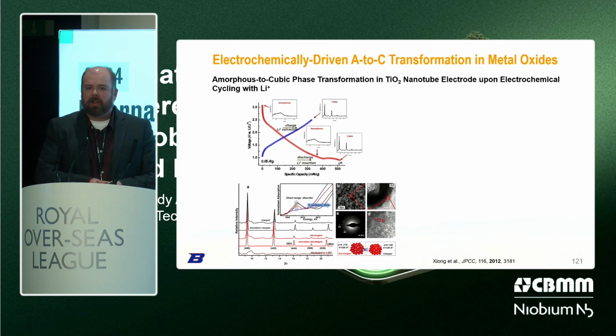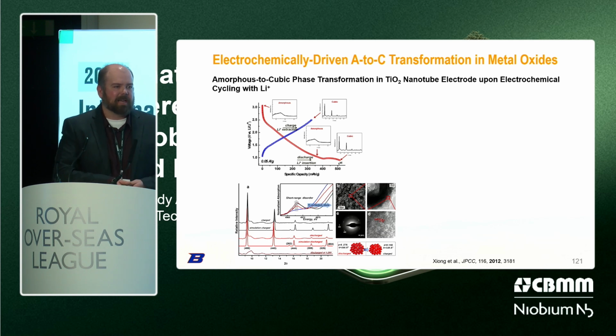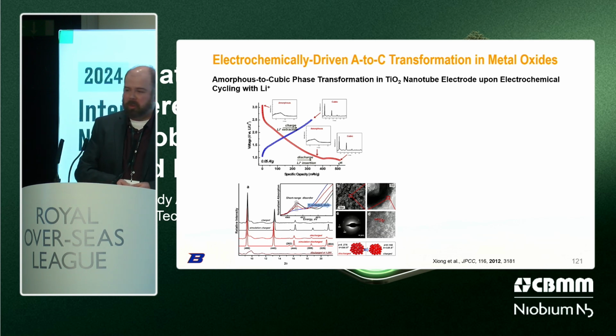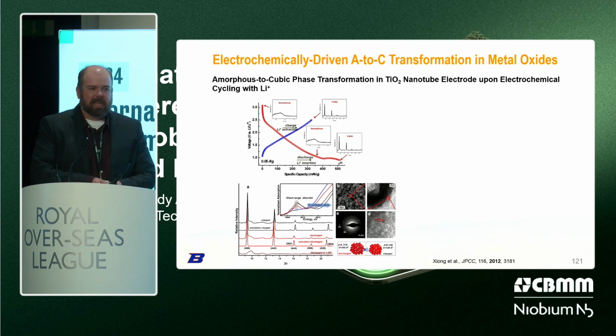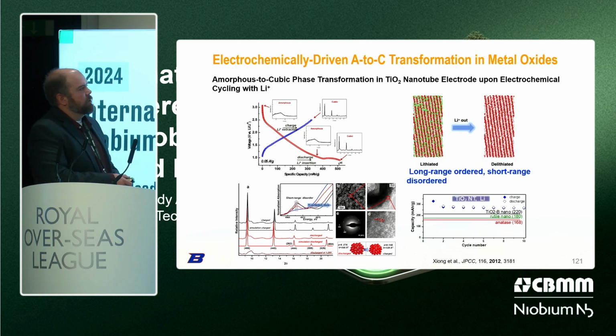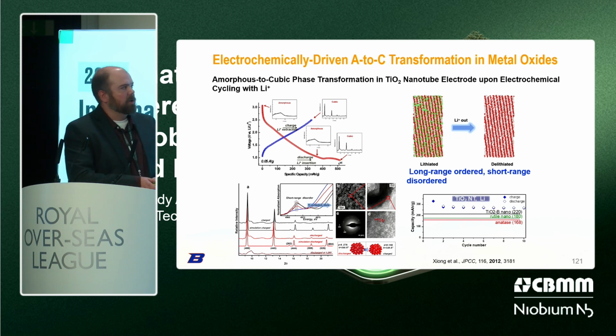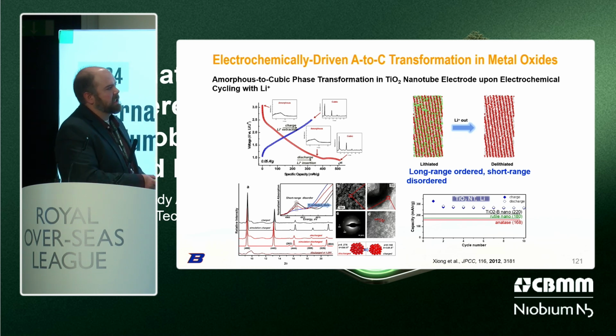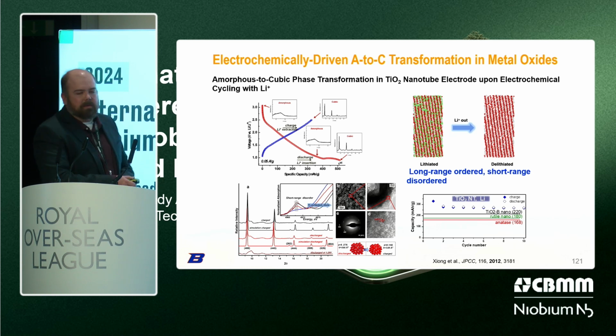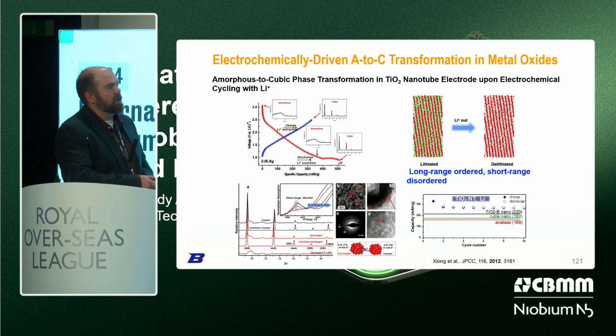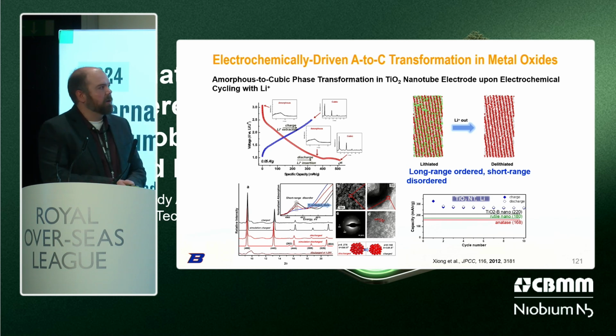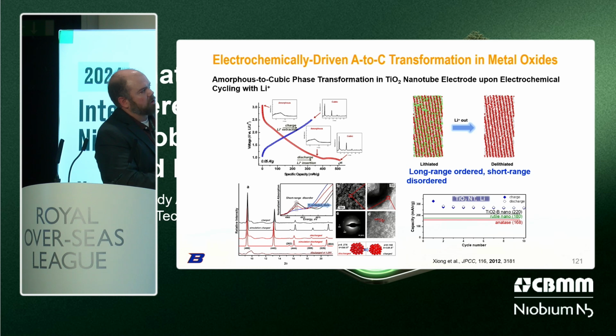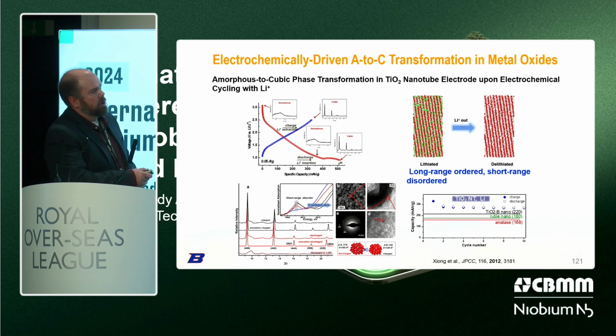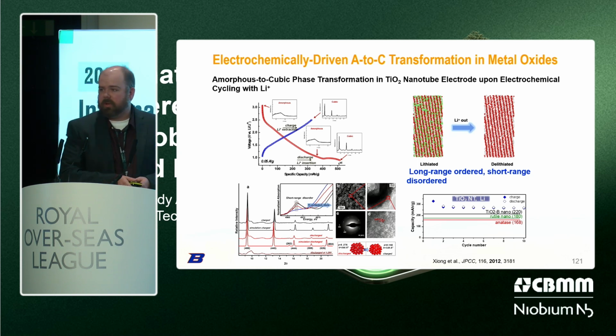It's kind of an odd approach to start a battery concept with an amorphous structure, right? Blocked pathways happen readily, but the idea is to incorporate amorphous material for a phase transition where you develop long-range ordering but short-range disorder. In this case, the lithium being pushed into the TiO2 created its optimal structure, right? It created this lithiated structure that became a cubic structure, which was then metastable enough to stick around after the lithium was removed.